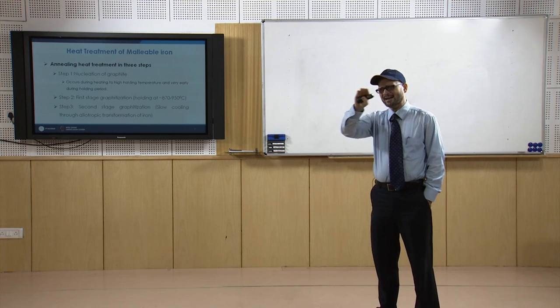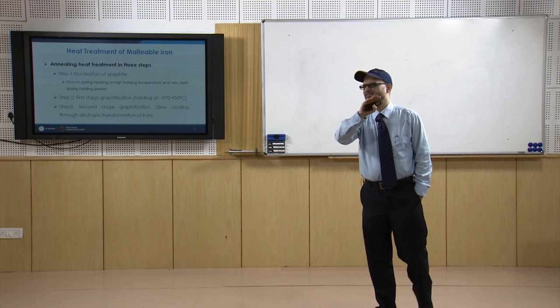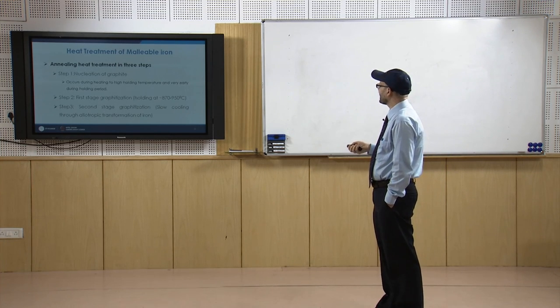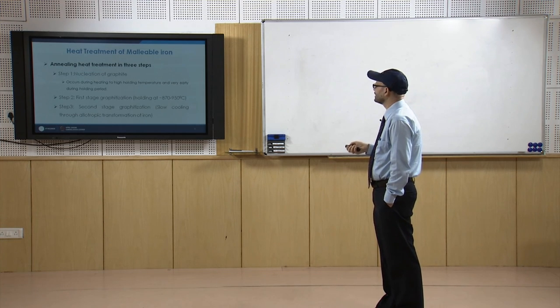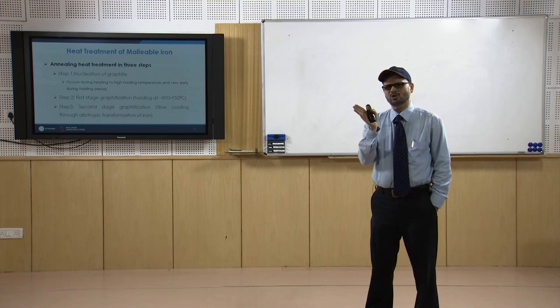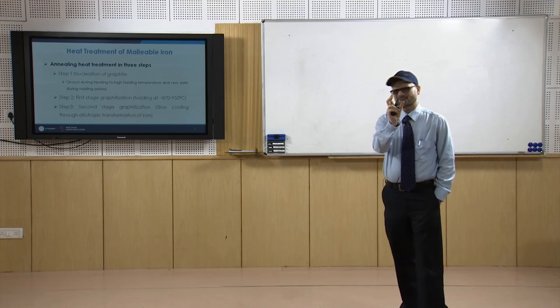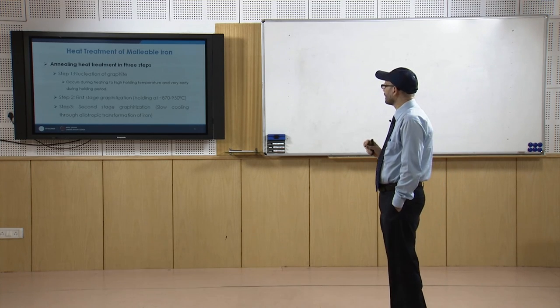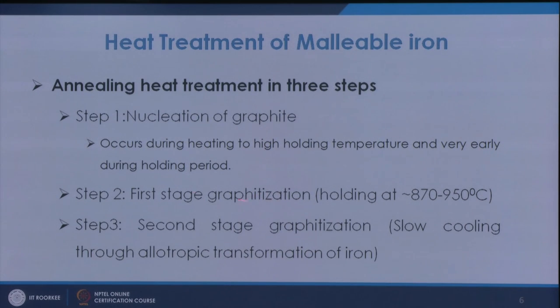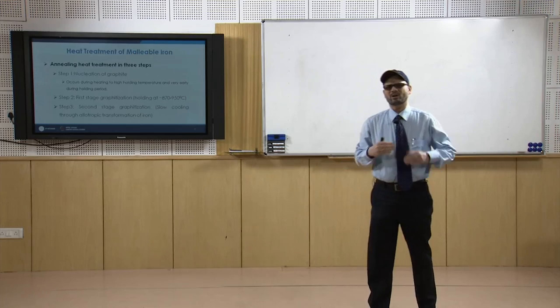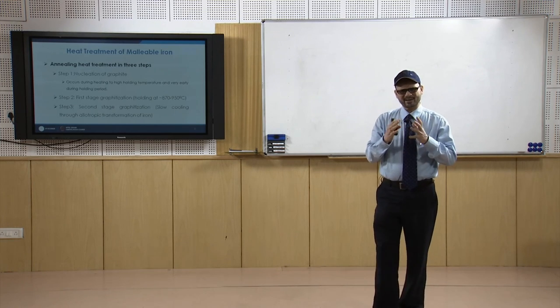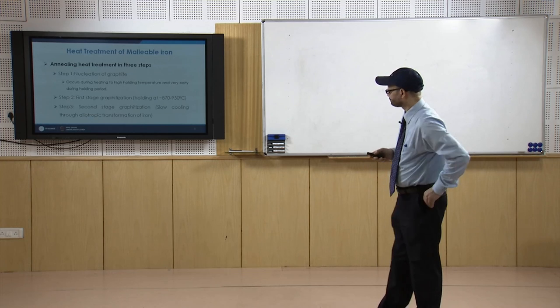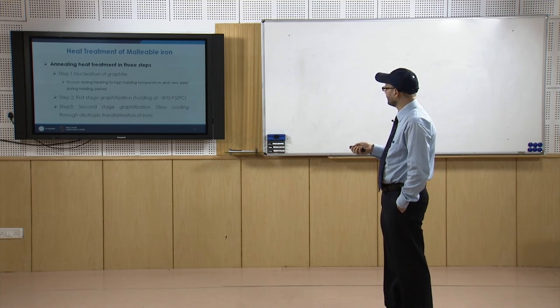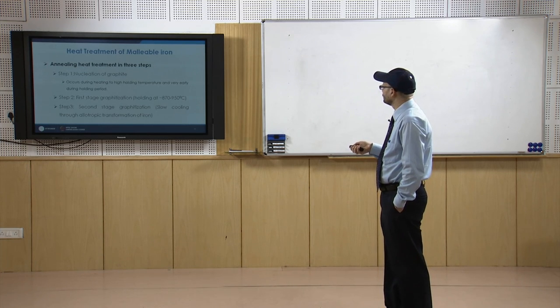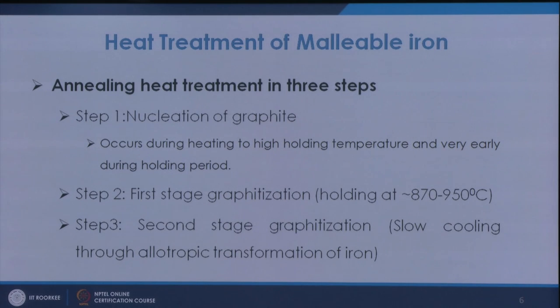Now, when we keep it at that temperature for very long hours, 40 to 50 hours, graphitization will take place. That is the dissociation of all the combined carbon into iron plus carbon. That is, Fe3C will dissociate into iron plus free carbon, and this is known as first stage graphitization. The first stage graphitization is responsible for the conversion of massive carbides into iron plus graphite or free carbon. Then the second stage graphitization during the annealing process is during the slow cooling through the allotropic transformation range of iron.